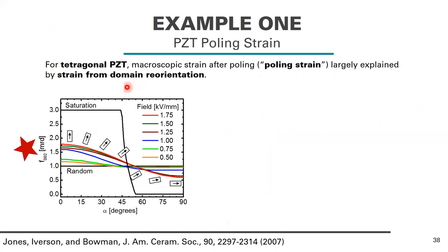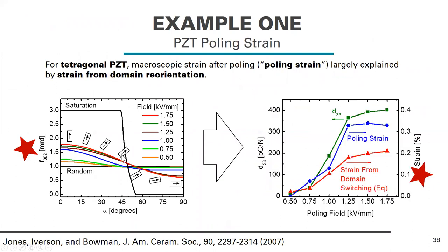For tetragonal PZT, the macroscopic strain after poling, or the poling strain, can be largely explained by the strain from domain reorientation. And so I think one of the first applications of this was taking this data that I showed you before and calculating, as a function of poling field, the strain resulting from switching.